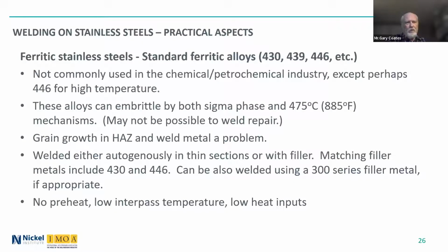Again, the grain growth is a problem. You can weld them autogenously in thin sections or with a filler. There are theoretically available matching filler metals for 430 and 446. They can be welded with a 300 series filler metal too, if appropriate. The 446 is often used where you don't want nickel, and so therefore welding them with a 300 series is not a suitable way of welding them.